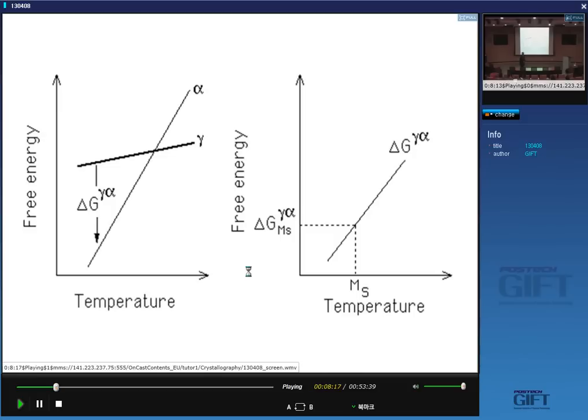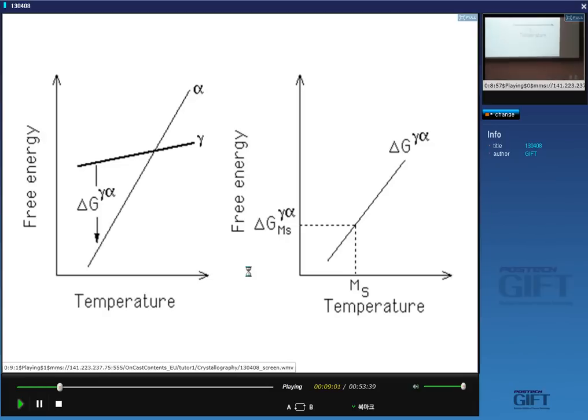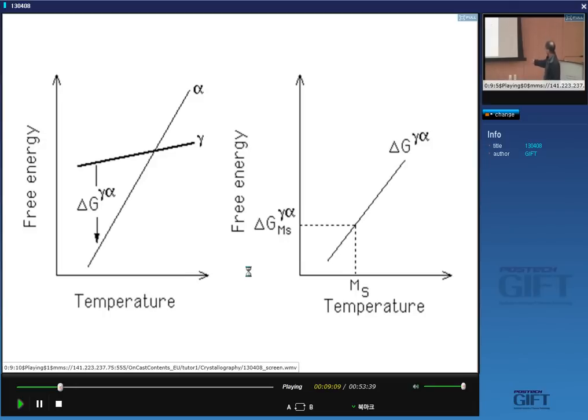You can calculate this curve very easily these days using software packages — for example MTDATA or Thermocalc — which allow you to work out the free energy of austenite and ferrite as a function of chemical composition, pressure, and temperature. You can even download free programs to do that. If you modify your composition — for example, add one weight percent of manganese — this curve would shift to a lower free energy change because manganese stabilizes austenite, and therefore your martensite start temperature would be depressed. So you've got software available which routinely allows you to calculate free energy differences as a function of alloy composition and temperature.